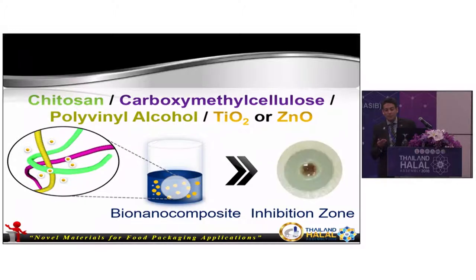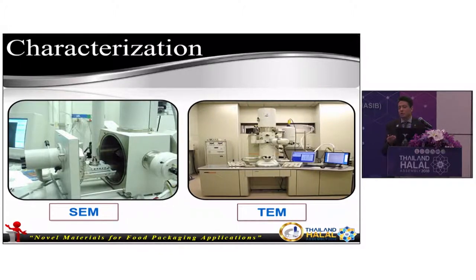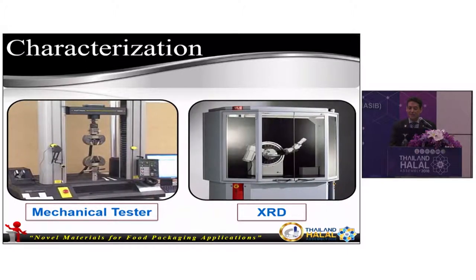The final product is called polymer bio-nanocomposite, and we start to make suitable characterization to prove the formation of the nanomaterial and polymer bio-nanocomposite using scanning electron microscope, which is used to determine the presence and dispersion of the nanomaterial on the surface of the polymer matrix. Also, transmission electron microscope is used to determine the presence of the nanomaterial inside the polymer matrix, and we study XRD to determine the presence and formation of the nanomaterial.